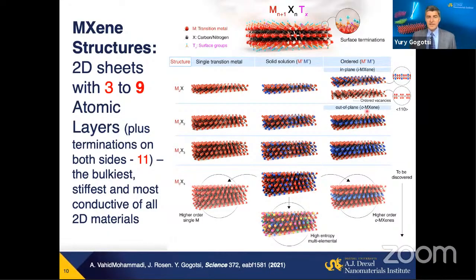And it's also possible to go further in atomistic design. It's possible to make materials with not only out-of-plane, but also in-plane ordering of elements, which are alternating columns of different metals. For example, yttrium and tungsten, scandium and molybdenum. So they're called iMXene, or in-plane ordered MXenes.